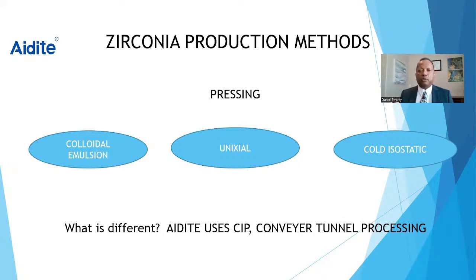The uniaxial process is where you take some material, you press it from 2 different sides, and then you place it into a mold, and you use compression to actually apply the forces, and it forms into a mold. One of the big disadvantages to this is the 2 sides that are pressed actually become very hard. It can be anywhere from 120 to 150 MPa. So the tool usage is minimized here. The internal density of the material might be okay, but the sides are very, very strong and hard. So this is not a very useful way of making zirconia, although many companies do utilize it. The first two that I've mentioned are somewhat inexpensive ways of making zirconia.